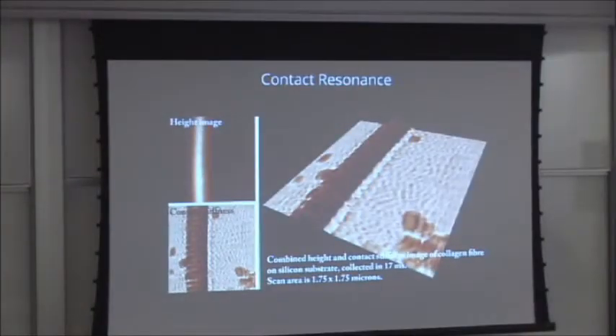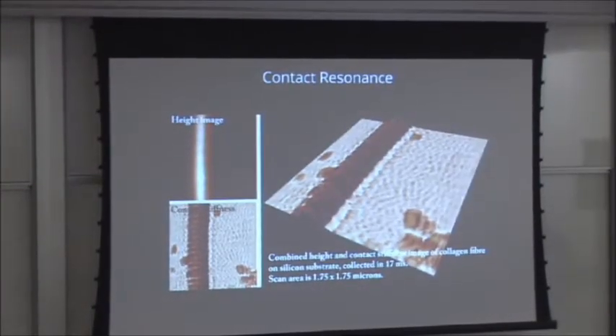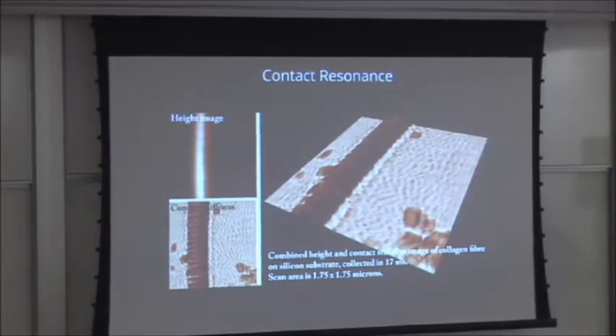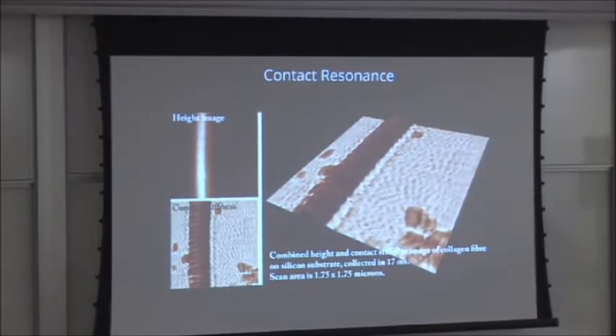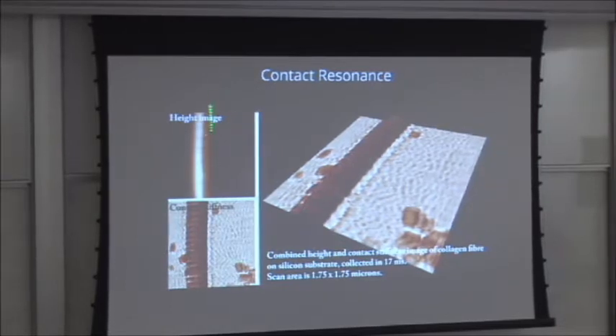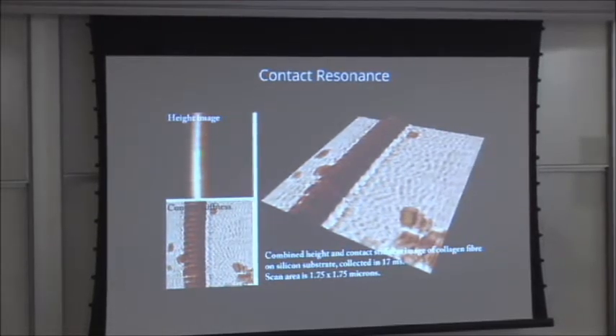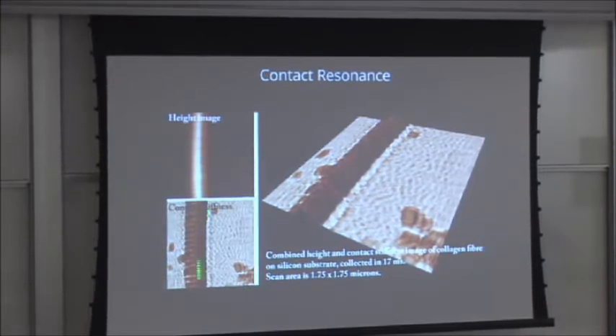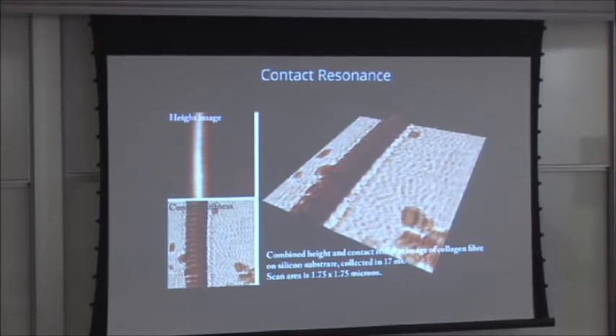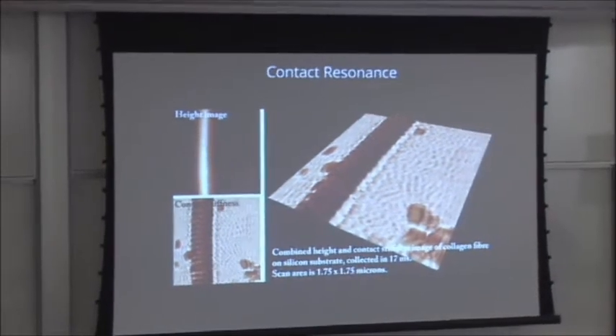So I won't go into detail what that is, but if you use contact resonance, it means you can get the stiffness out of the material in contact. And so here's the collagen again. Here's the topographic image. High is white, low is dark. But here's the mechanical property at the same time. So you can see that the collagen is softer than the silicon substrate. So we're able to map in 17 minutes not only the image, but also the mechanical properties.